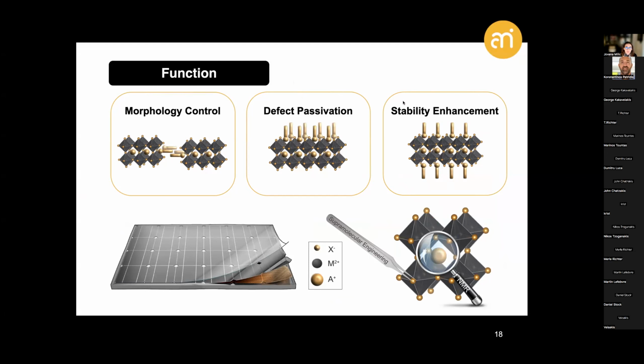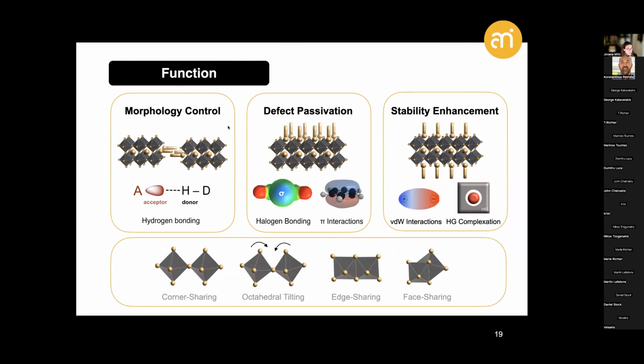Now, each of these functions can be translated into a set of complementary supramolecular tools to address them, such as, for example, using hydrogen bonding to tailor the morphology of these materials, as illustrated here, for instance, cross-linking different perovskite phases or affecting their general structure, more indirectly affecting the resulting properties, but also affecting their optoelectronic characteristics, for example, by directing this octahedral connectivity that is directly affecting the optoelectronics, since it's defined by the metal halide orbital